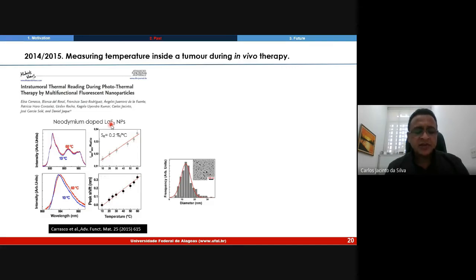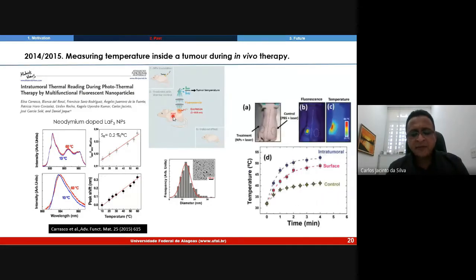It was so interesting that it was possible to make measurements of the subcutaneous intratumoral temperature in real time. So, using one excitation to induce the local heating and another excitation to detect the luminescence of the material and convert it to temperature. In fact, the therapy was so effective that in 5 days the tumor was completely destroyed. In the graphic here, we present the control, without the tumor, the surface temperature using a thermographic camera, and the intratumoral temperature using the luminescent nanoparticle. Look at the difference between here.